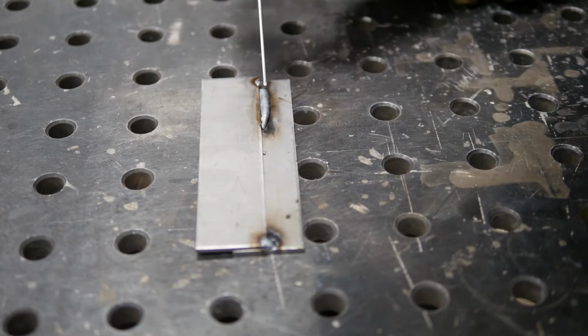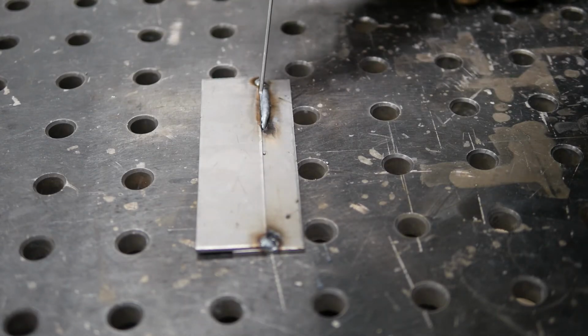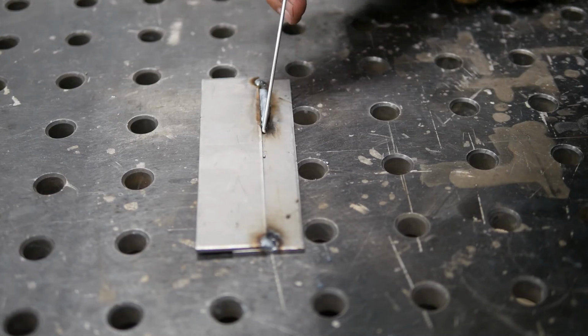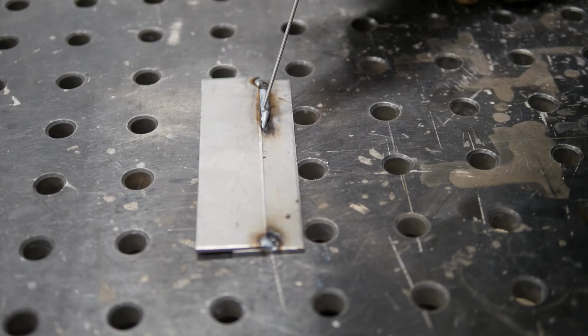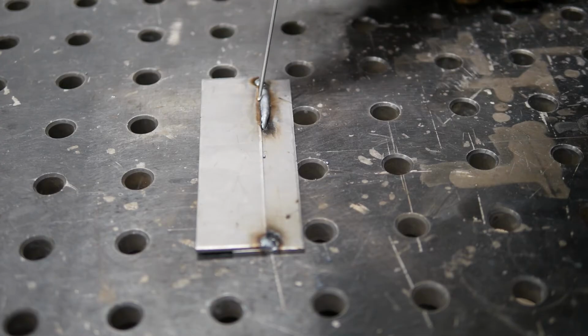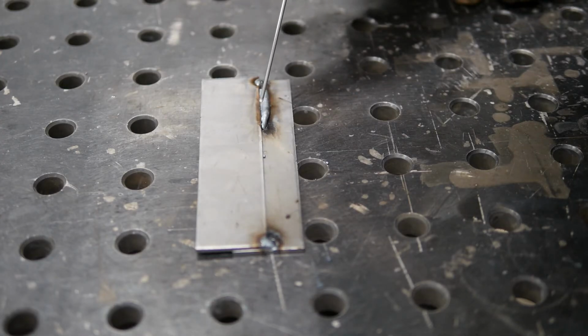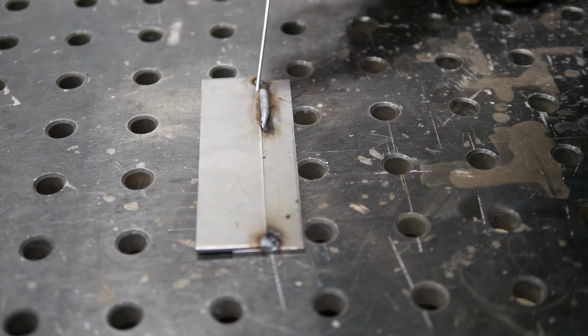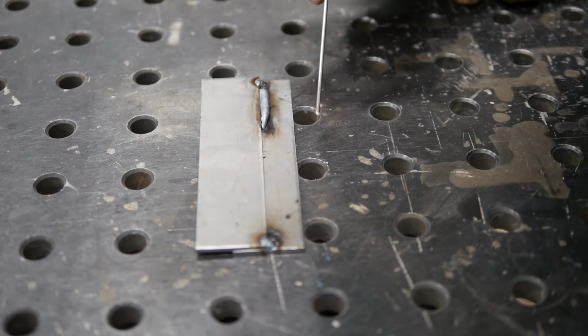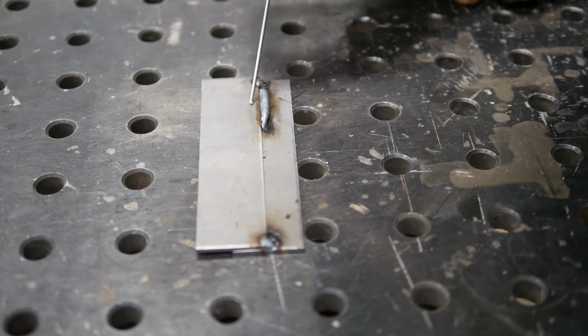So right off the bat, what I heard is the arc was just not very stable. It was popping and cracking, and it just wasn't very smooth. Now, I felt the gun was stubbing back and forth, and that's because that arc length, again, was way too small, way too focused, and you can see what it did to the bead. You can see how convex this bead is. Now, when we turn the voltage up and we relax the bead, then this bead's basically going to sit really nice and flush against the material.